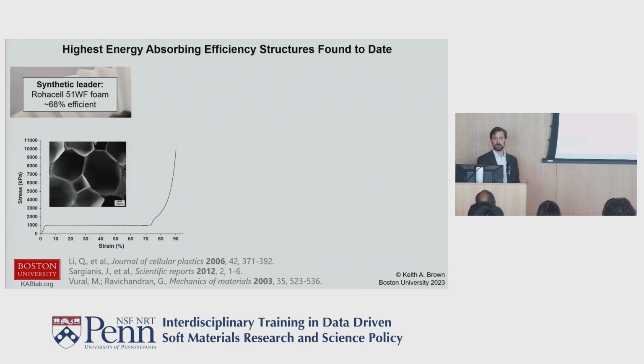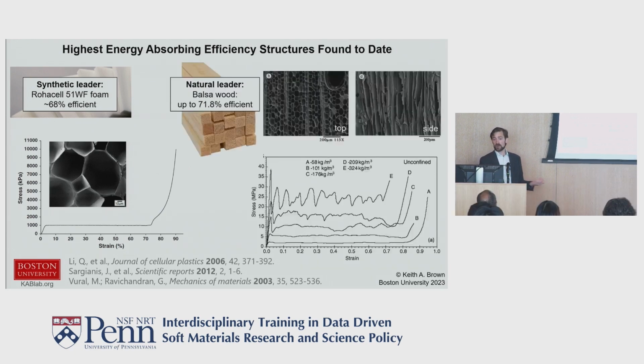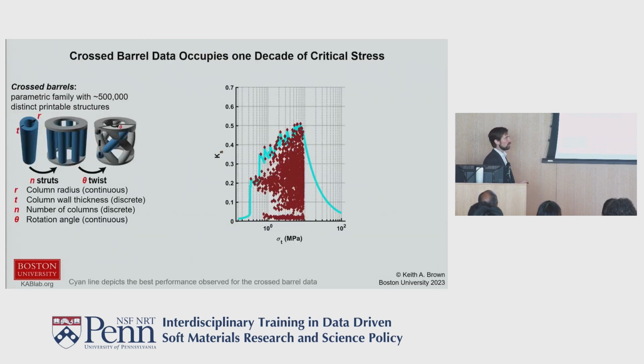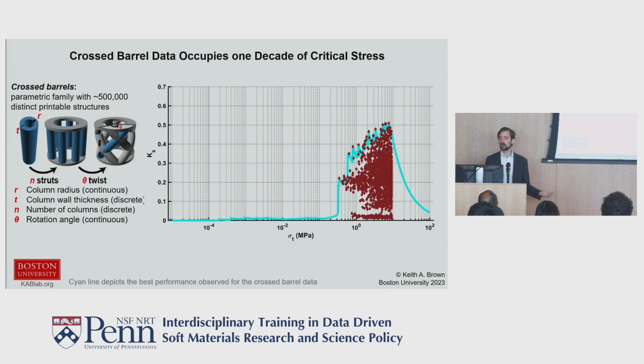Beyond that, is that the best thing we've ever found? The best thing we found, period, was nature. We've yet to beat nature, which is balsa wood, just under 72%, so 71.8% efficient, by one report. So we have a lot of room to go: we get to the 50s with 3D printing, and nature gets to the low 70s. Another challenge to bring up is that this is the cross barrels, a relatively narrow range in working stress. Ideally, we would like to optimize over a much, much larger range.